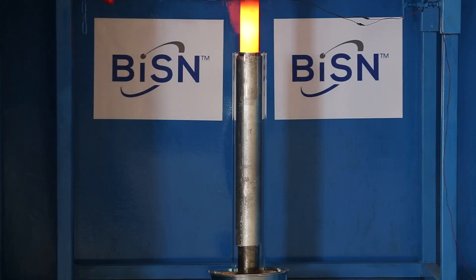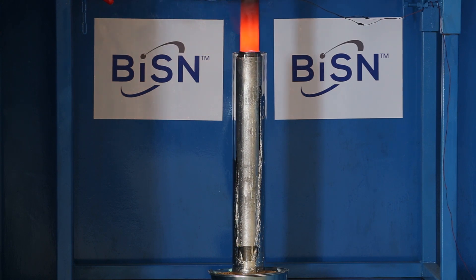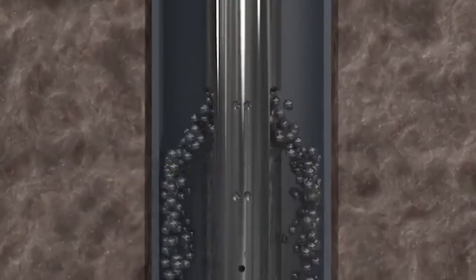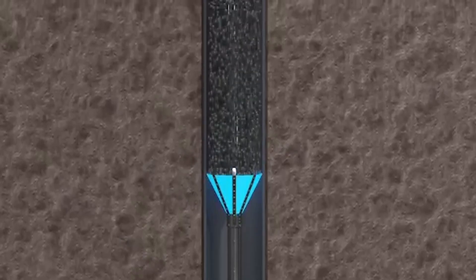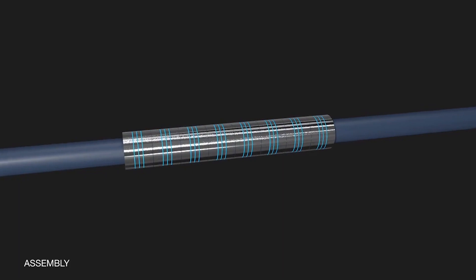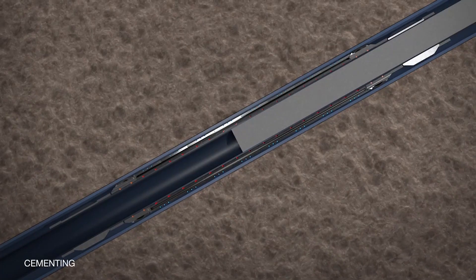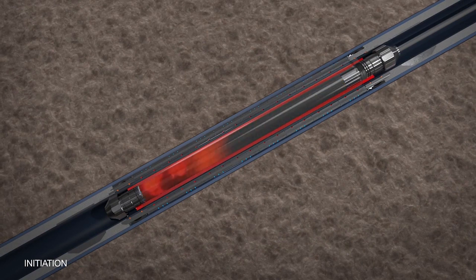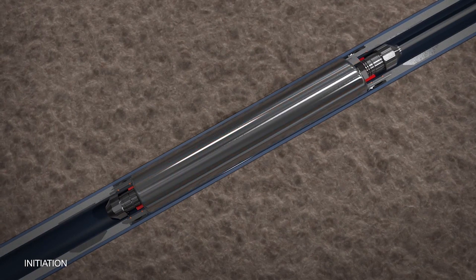We use the alloy in different applications and transport it downhole in different ways. Sometimes we have it cast on the outside of the tool; other times we use it in shot form, like little BB shot. In other cases, such as a completion tool, we place the alloy on the outside of the inner string just like donuts — they're then cemented in place, and we run inside the well with a heater afterwards and melt the alloy once it's all in situ.